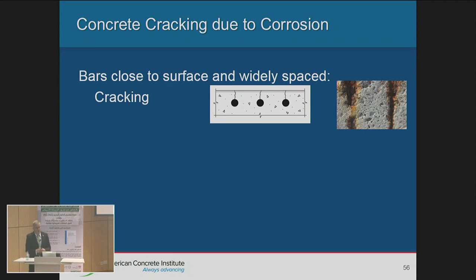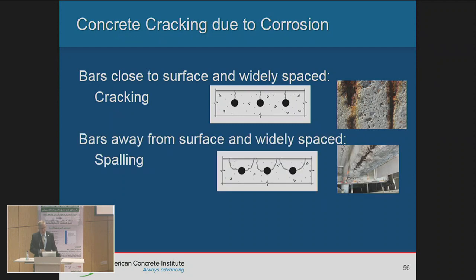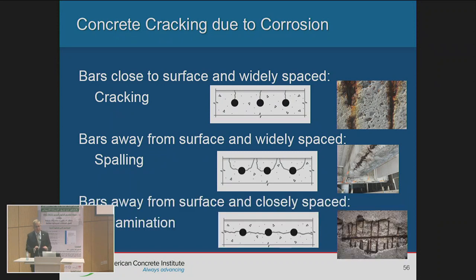Now, how would you recognize, for example, cracks or deterioration due to corrosion? If your cracks are close to the surface and widely spaced, you get the cracking, and those will be telescoping to the top of your concrete member. And those will be separate cracks. If the cracks are away from the surface and widely spaced, you'll get that spalling or pop-out at each location of your bar. And if they're deep, if they're away from the surface and they're close together, that's when you get your delamination.